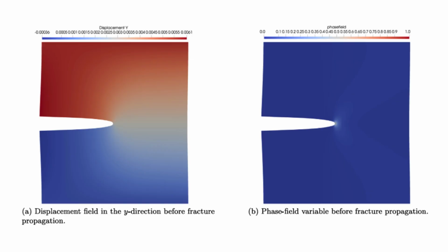It showed this sort of nonlinear increase in stress before the final break. Because the AT2 model diffuses damage a bit even before total failure, the material softened slightly. It wasn't just a straight line up to the peak stress. Okay, so it captured that pre-failure damage effect correctly. Makes sense. What was next?